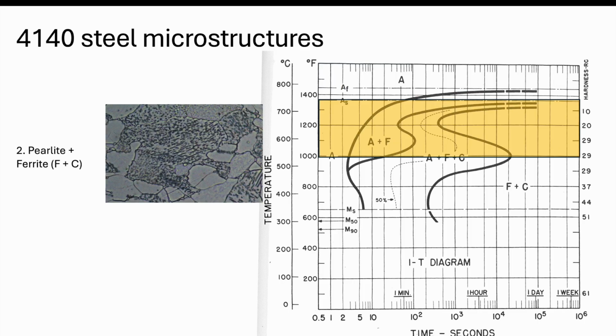So in the next band below, in this band of about 750 or even lower to about 550 Celsius, this is our pearlite range, and specifically pearlite plus ferrite. So you see an F here. That means that ferrite forms at the smaller or less time, and then as we go on in time, we form F plus C, and that is pearlite. So this yellow band that I show here is pearlite plus ferrite.